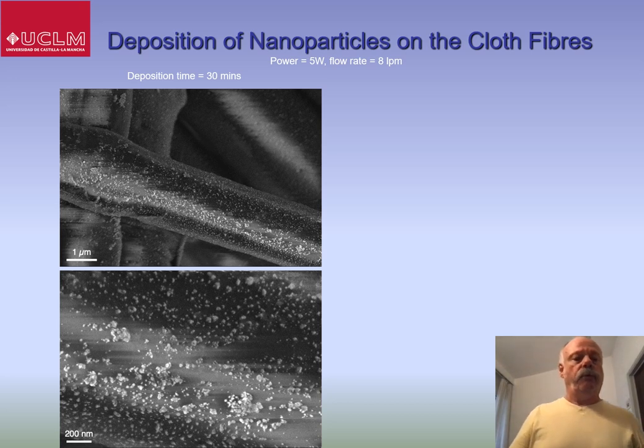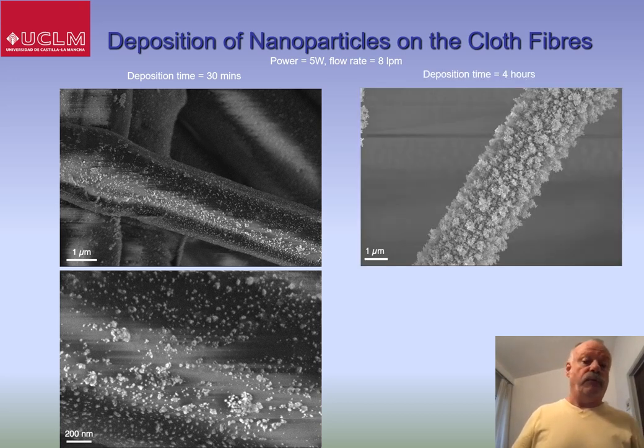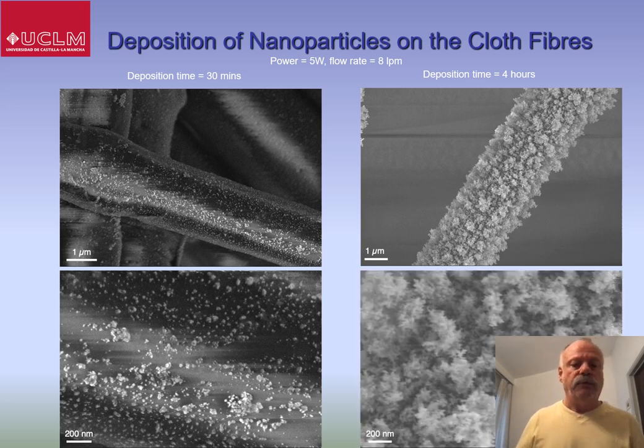And then going to a higher deposition time, this time 4 hours, you can see a very high density of silver nanoparticles on the individual fibres, a totally agglomerated film. And again, in more detail here, you see this very highly porous coating on the fibres, but with individual nanoparticles.